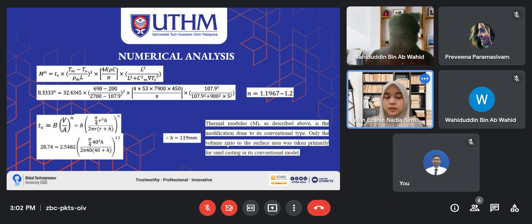By using the equation, the calculation and simulation analysis of geometric shape for cylinder is evaluated. Then we got n equal to 1.2. As for that, temperature hotspot distance was calculated using the injection point as the origin and verified with simulation analysis. So here we got H is equal to 119 millimeter. Simulation analysis for a cylinder shows that the thermal peak is approximately 49 millimeter from the origin. That's all from me. Thank you.